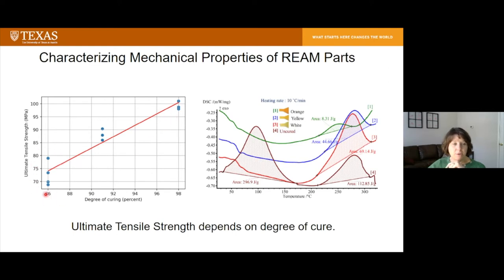So low degrees of curing, sort of white parts, yellow parts, orange parts, you can see that there's almost a perfect correlation between the degree of curing and the ultimate strength of those parts.